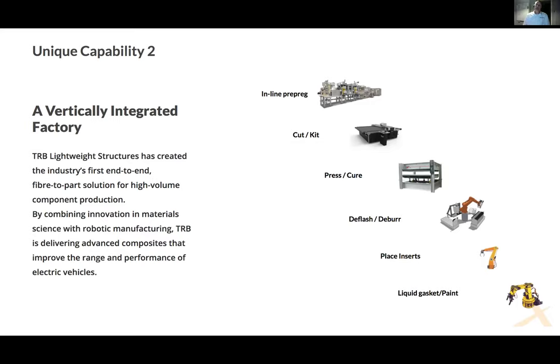The second challenge was then putting everything in line. What's really important for this is getting to a much higher yield of automation. As a business, we have a lot of experience in the manufacturing of materials. We have a lot of IP in different resin systems, from epoxy systems to cyanate ester systems, etc. So we've really solved the challenge in terms of the material costs. Now we're manufacturing the material at our site in Richmond, Kentucky, on our own pre-preg lines. These are lines that we have manufactured ourselves, bespoke to the resin systems and the requirements of specific customers.